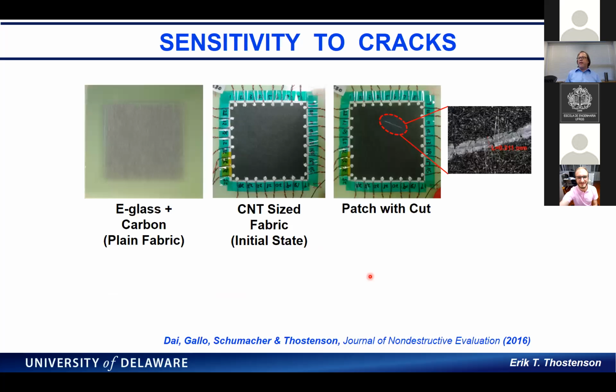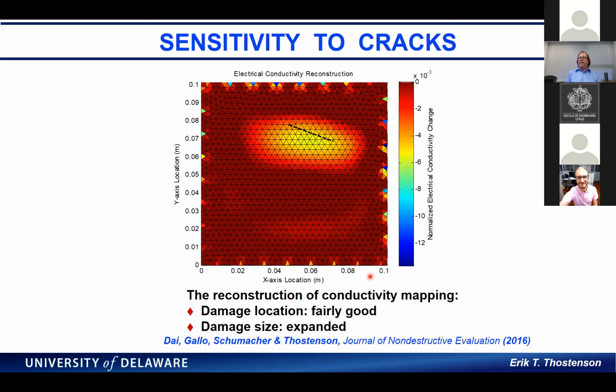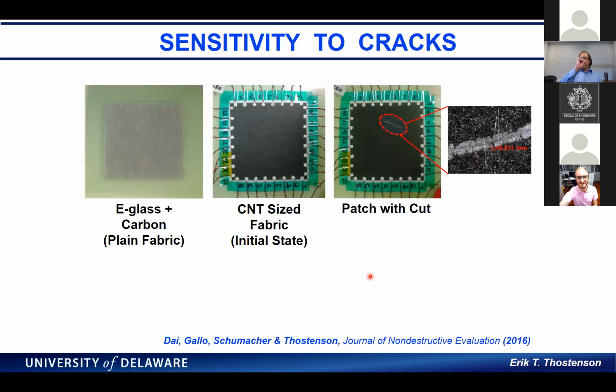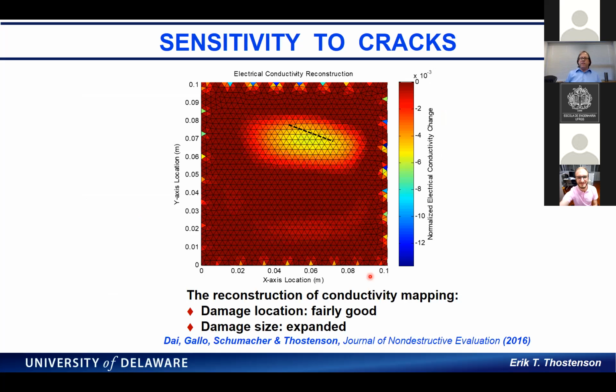This is another case where we looked at, well, can we use it to detect cracks? And so what we did is we basically cut a crack into the patch. And again, we could detect the damage location within reason, although the damage size was expanded, and it's partly due to the slightly anisotropic nature of the composite.